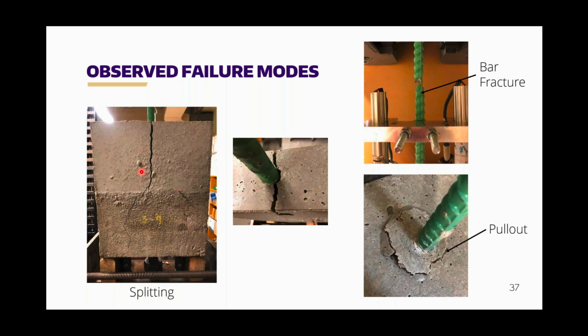That safety restraint that Carolyn was showing you, which went around the concrete block, was just meant to help restrain this crack and make sure that it didn't go all the way through. That was really just to protect the instruments. So it was only snug tight. It wasn't meant to confine anything. It was mainly just there to arrest this crack before it reached the bottom and split the specimen in half. You can also see bar fracture and pullout, and those are going to be at the extreme ends of our design space. And I'll explain a little bit more about those points in a moment.